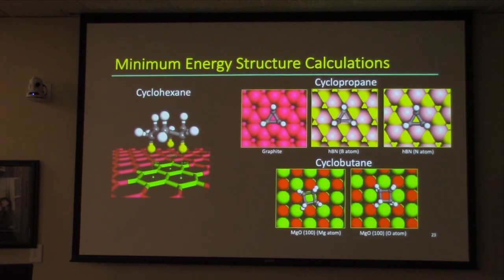But one of the first things we do is just do a simple energy minimization calculation. We just calculate how the molecule interacts with the surface. We cover the whole surface by taking advantage of their symmetries. So we break them up a little bit, then just reorient the molecule and run an energy minimization calculation. All that says is we look at all the different configurations and we sort out the lowest one, and then we take a look at those.